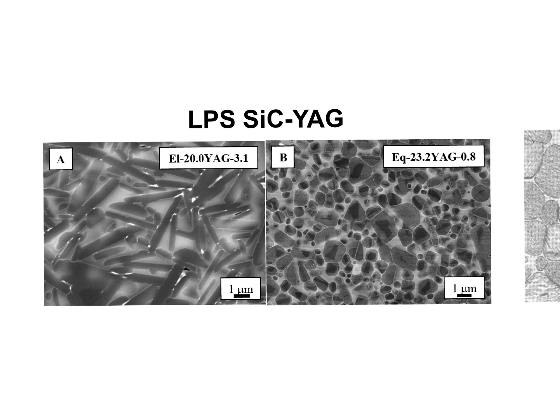And this is just showing you, at one concentration of YAG, we have these whisker-like shapes of silicon carbide, but if we go to a slightly different concentration of YAG, now the silicon carbide has turned into nice grain-like shapes. We like this, all right? This obviously will densify much more efficiently under gravity than the one on the left, okay? So hopefully it's obvious that the one on the right is going toward an efficient grain boundary-based structure.